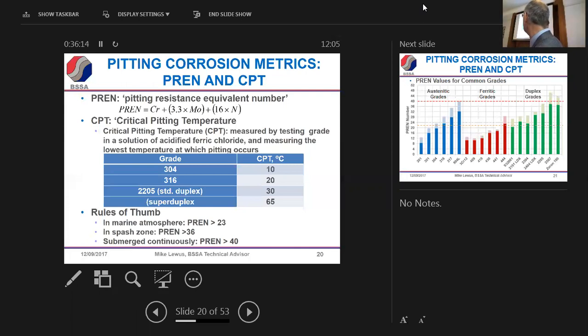You can see 304, critical pitting temperature 10, 316, 20, etc. 2205, superduplex. So if you need something more resistant, there's always a place to go. As it turns out, 304, well, when people ask us, we don't recommend using 304 in a marine atmosphere.